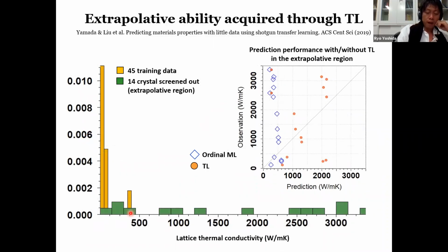Here, I'd like to describe the great potential of transfer learning in terms of extrapolative ability. This histogram shows the distribution of the 14 crystals that we discovered, indicated by green. Some of them reached more than 3,000 watts per meter Kelvin in thermal conductivity. On the other hand, our training data, denoted by yellow, are distributed in a much lower region. Our model is trained on this data set and makes predictions for these materials.